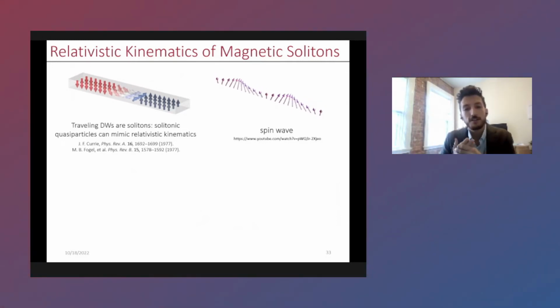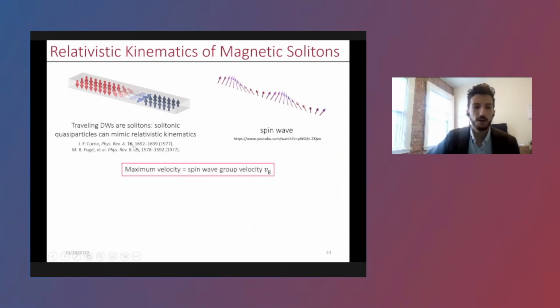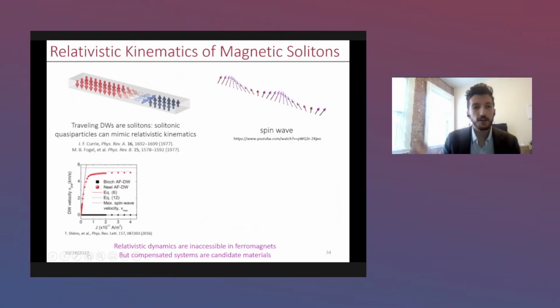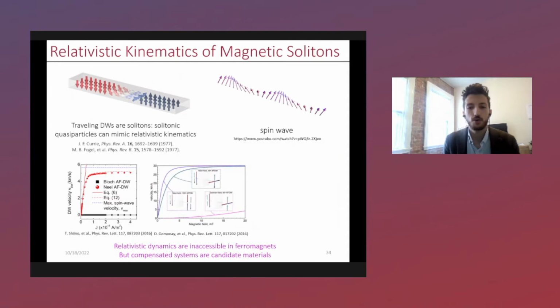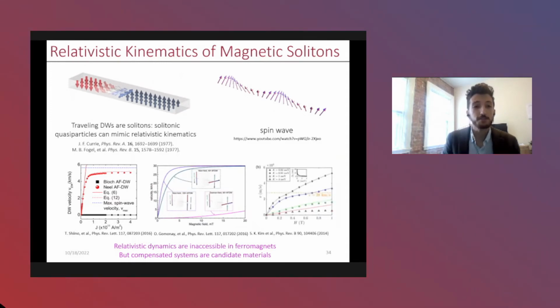So what limits the velocity of a domain wall is really what limits the spin wave group velocity. In other words, the maximum velocity of the domain wall is the spin wave velocity. And this was proven algebraically and analytically by a number of groups in the 70s and 80s. And even more recently, this effect has been shown using computation. Atomistic simulations and other types of simulations have shown that this limit does indeed exist, and they even propose material systems to access this limit, particularly compensated systems.